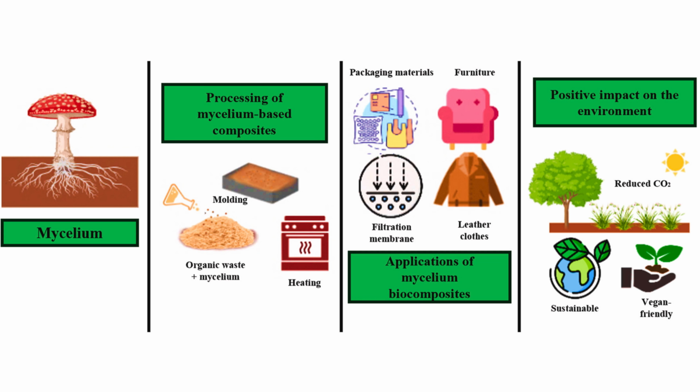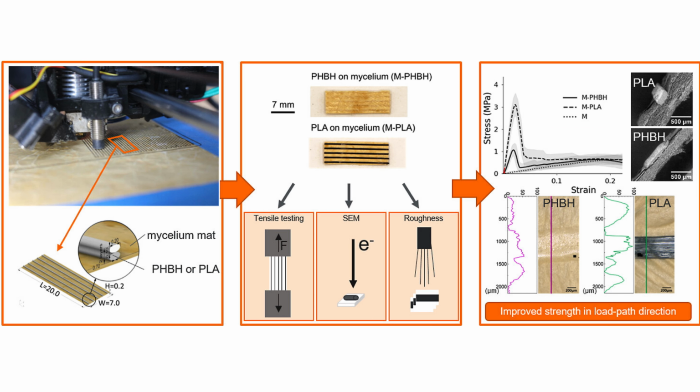Other treatment processes of the fungal biopolymer have been identified to be mainly chemical treatments, which serve to further enhance the strength of the materials. For instance, treatment with glycerol, plasticizer, and a hydrophobic bio-based binder was observed to increase the flexibility, tensile strength, and water-repellent ability of a fungal-based leather substitute.